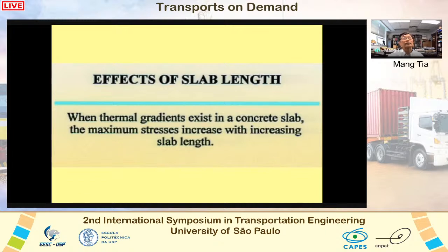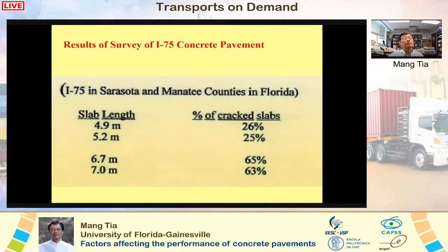Thus, we can summarize by saying that when thermal gradients exist in a concrete slab, the maximum stresses increase with increasing slab length. And this conclusion was validated by our observation of cracking in the concrete pavement on I-75 in Sarasota and Manatee counties. The slabs of longer lengths of 6.7 meter and 7.0 meter cracked more than the shorter slabs of lengths of 4.9 and 5.2 meter.